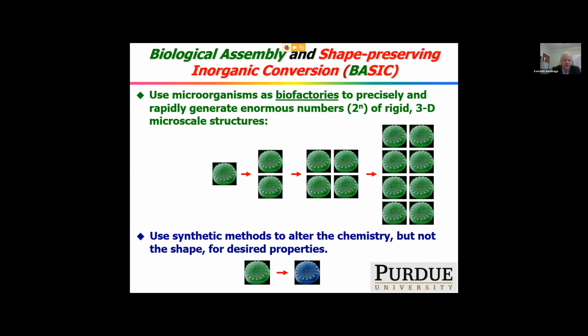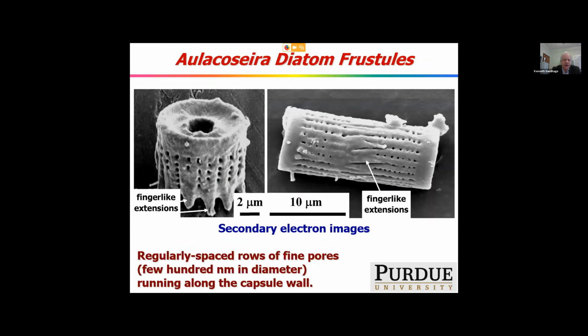And as I show you schematically here, we can then change the chemistry, but not the shape and even the nanoscale features. So one of our diatoms I work with quite a bit is called Aulacoseira. It, like all diatoms, has two halves to its frustule. On the right, you see an image with two halves with overlapping finger-like extensions. It's a cylinder with submicron scale pores that run along the cell wall length.